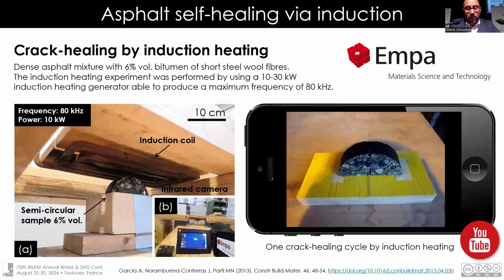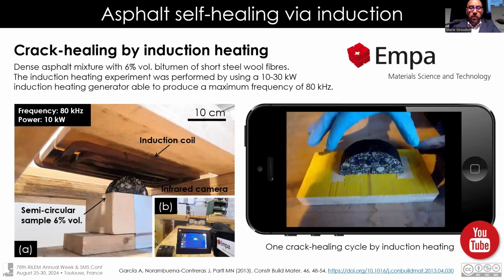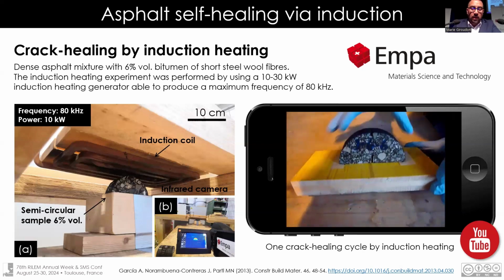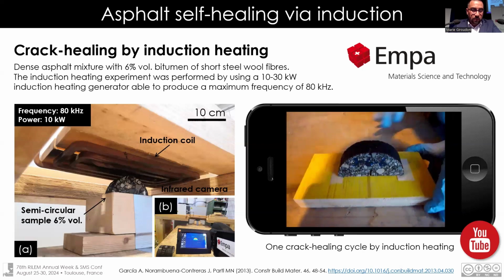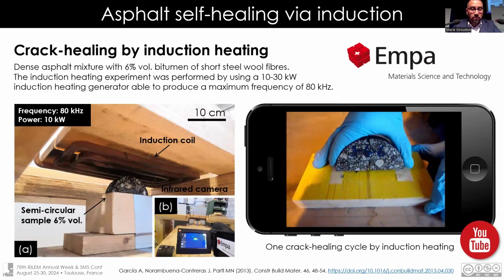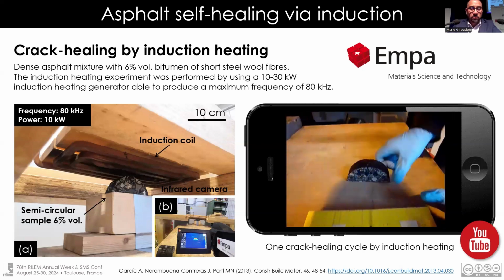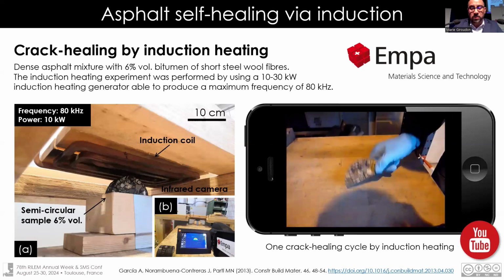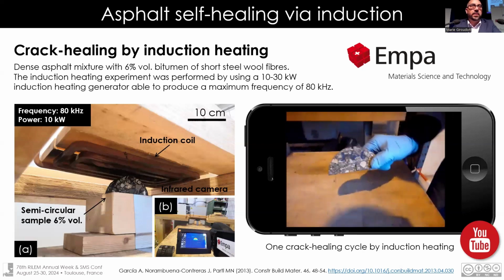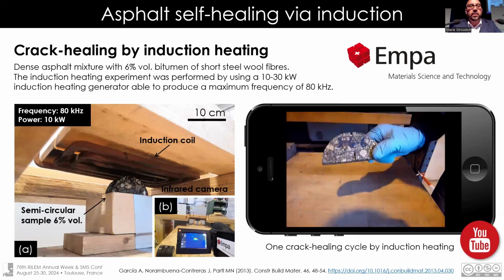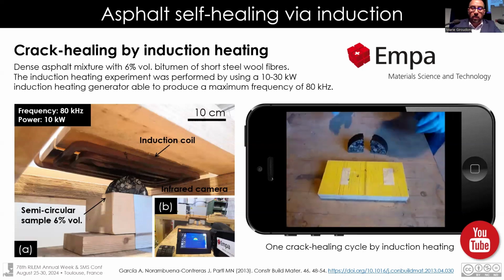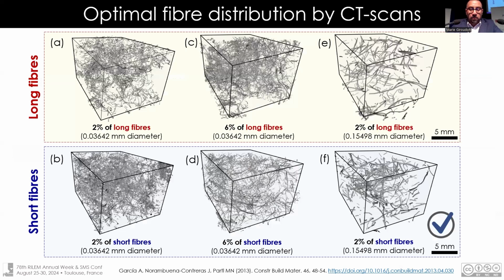After the sample cools to room temperature, we can manipulate it and check that the crack has been healed. Let me show you. But obviously, we must quantify the healing index before and after heating using mechanical properties, using different indices in order to evaluate the self-healing properties. These samples contain fibers, steel fibers explicitly, so it is important to evaluate their distribution within the samples, for example, by using computed tomography.